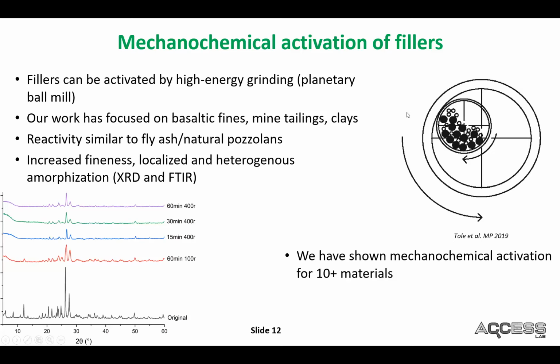So fillers can be activated essentially by high energy grinding as well. We've looked at a lot of basaltic fines, mine tailings, and clays as well. We've actually demonstrated mechanochemical activation for 10 plus materials, and again, you get similar reactivity to fly ash or natural pozzolans.